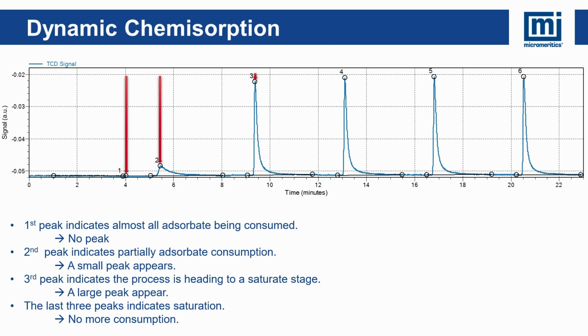So let's look at the first pulse. When hydrogen gas is injected into the system, it is completely consumed by the platinum catalyst. This suggests that all available surface sites on the catalyst are actively engaging with the hydrogen and adsorbing it. On the graph, there is no peak after the injection, indicating that no unreacted or residual hydrogen is eluted from the system, meaning it is fully adsorbed or reacted.